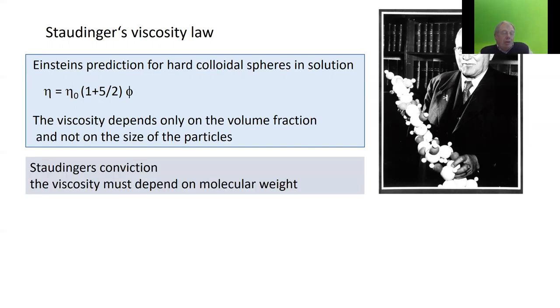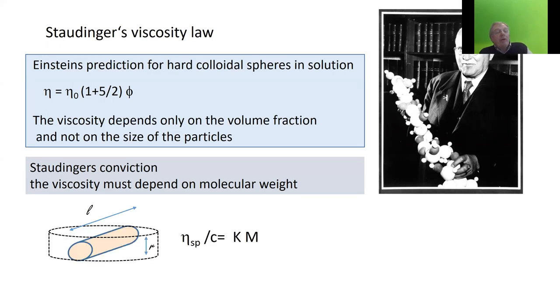So Staudinger was sure, and he measured this actually, that the viscosity must depend on the size of the molecules, on the molecular weight. So he developed his own equation. He assumed macromolecules are stiff rods, very much supported by his wife, who believed that the grass would crumple or fall down if these macromolecules, the cellulose in there, were not stiff rods. So he considered the macromolecule a stiff rod that tumbles around in a plane to take up the volume of a disk. Because the volume of the disk is proportional to L squared, the radius of the disk, he got a relation that the viscosity is related to molecular weight with the power one, or directly proportional to molecular weight. Great equation.